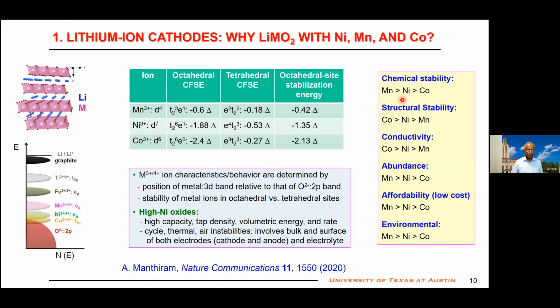So when you increase nickel, the nickel band is barely touching the top of the oxygen 2p. Therefore, you can go all the way to nickel 4 plus. So you can extract more lithium, unlike in the case of cobalt oxide. So you can get higher capacity. That's why everybody is interested.